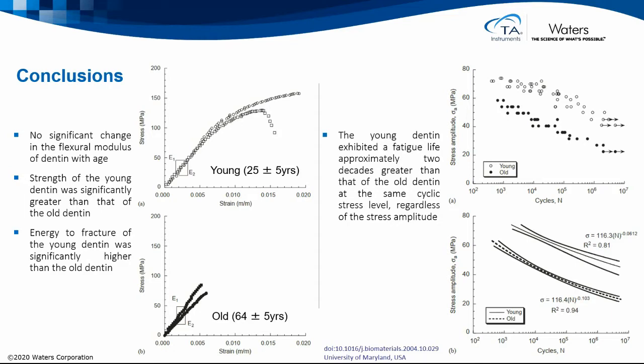And now you see a significant reduction in not only the strength, as we saw on the left, but we see that played out over time in terms of oscillating load as well. So for example, if you said for 50 megapascals, if you imagined a line from 50 and you draw that over, you see that the older samples will last something like 1,000 to 10,000 cycles of repetitive loading. But if you take that and draw further over to the cluster or the line in the young data, now you'll see that will last almost 1 million cycles. So now you see that length of time is significantly longer for the same amount of stress. And as these teeth get older, they become much less resistant to repetitive loading.